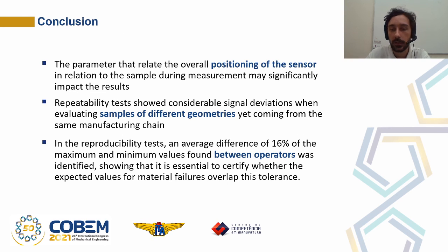For the conclusion of this study, three factors gained the spotlight when evaluating the variability of the Barkhausen noise signal: positioning of the sensor, complex geometries, and different operators. In the reproducibility test, an average difference of 16% between the maximum and the minimum values was identified between operators, showing that it is essential to certify whether the expected values for material failures overlap this tolerance.